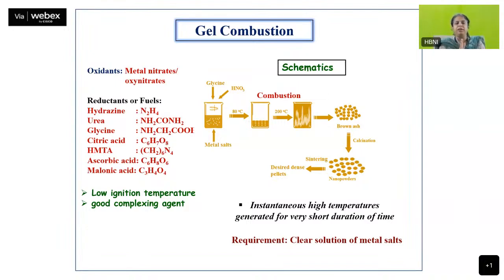And we suddenly increase the temperature from 80 to 100 to 300, the hot plate maximum temperature. It shows combustion. For that fraction of a second when the combustion is going on, the temperature rises depending on the fuel, nature and quantity. It rises to as high as 1400, 1200, 1300 for a fraction of a second. In that fraction of a second, either you get directly your product or you get the precursor to the product, which can be heated at lower temperature to get the final product. This is what combustion is. So you get instantaneous high temperature generated for a very short duration of time.